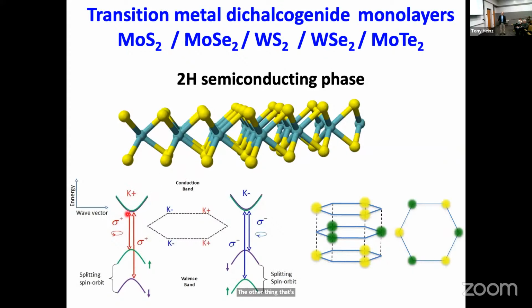You have regular parabolic bands. And unlike carbon, where you have weak spin-orbit interactions, these are heavier elements, and you have significant spin-orbit interactions with a big splitting in the valence band and a small splitting in the conduction band.